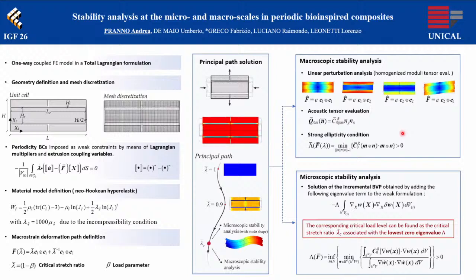While when we focus on the microscopic stability, which is useful in composite materials with a complex microstructure, we use a microscopic stability analysis. So a second subroutine has been implemented to evaluate, in a sequential way for each loading step, the minimum eigenvalue associated with the microscopic structural stability function. The macroscopic stability, as you can see in this slide, was detected for an increasing assembly of unit cells, because the macroscopic stability can be obtained by monitoring the strong ellipticity condition.